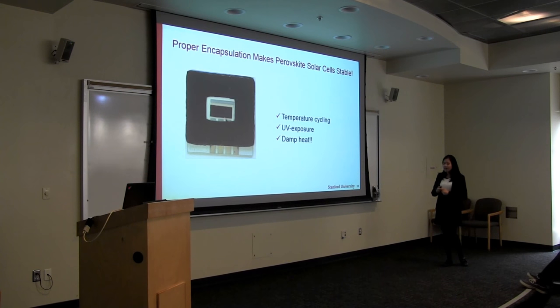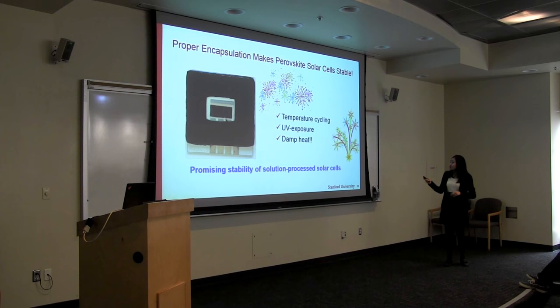So I hope that I have demonstrated and convinced you that if we properly package perovskite, it can be stable through a temperature cycling test, meaning it can be mechanically robust. It can withstand the UV exposure, and it can finally, actually for the first time in the field, pass the damp heat test that everyone is concerned about. And with this promising stability result, we can then take the solution-processed perovskite solar cell, which has a very high performance, to have a comparable cost to other types of solar technology, and then it can be out in the industry.